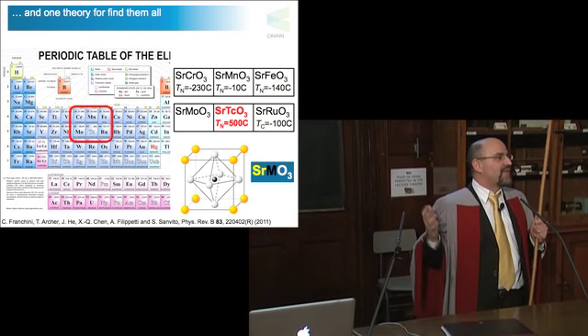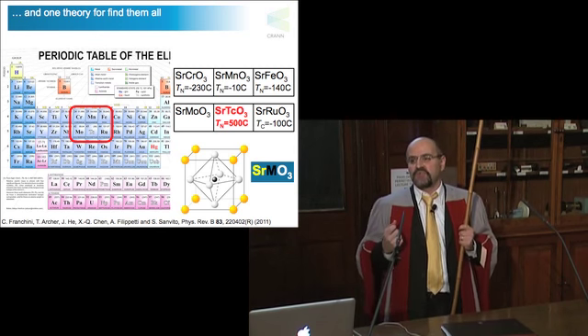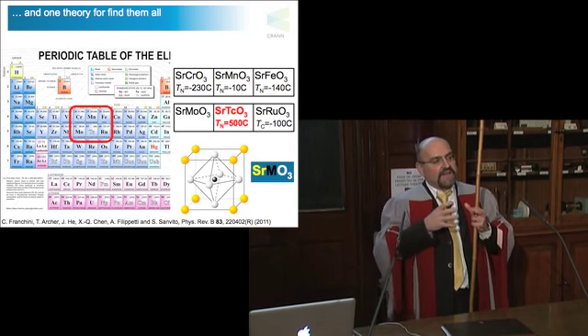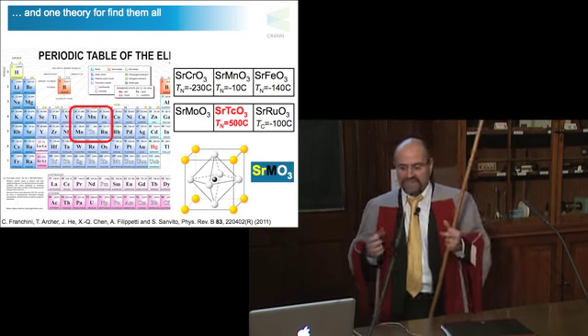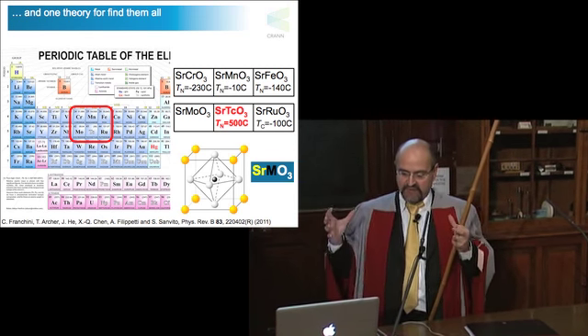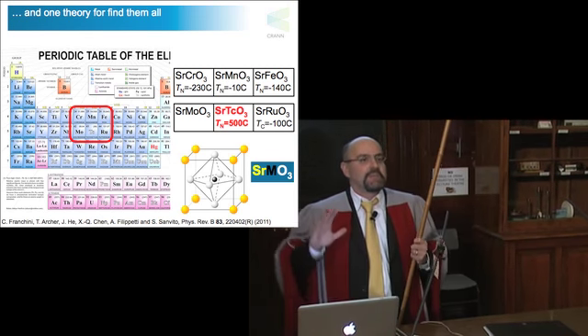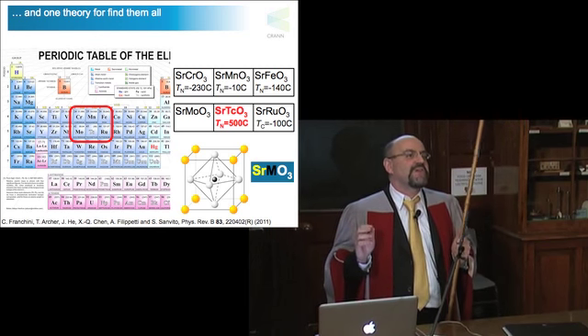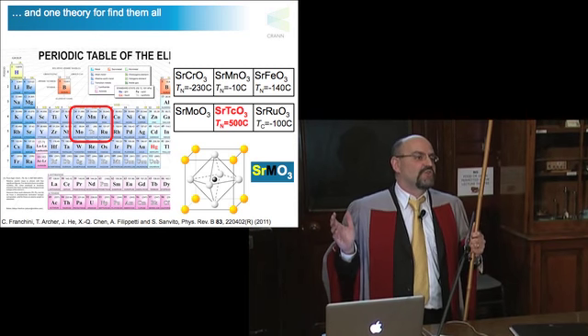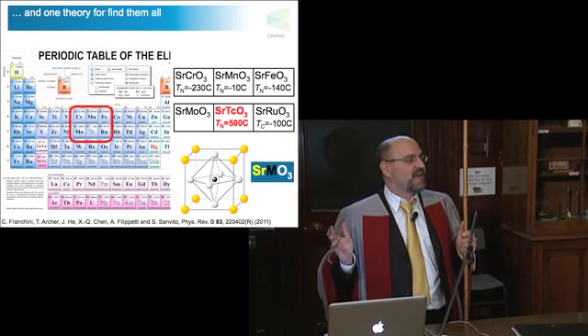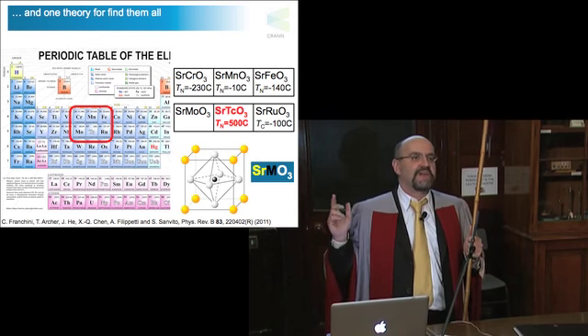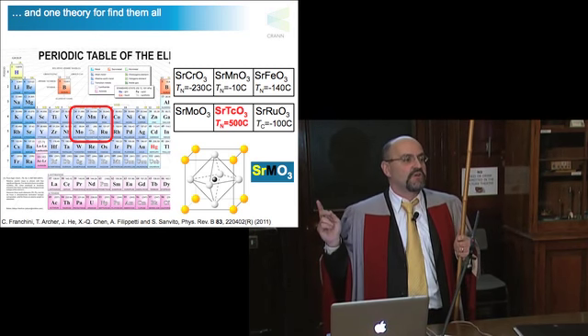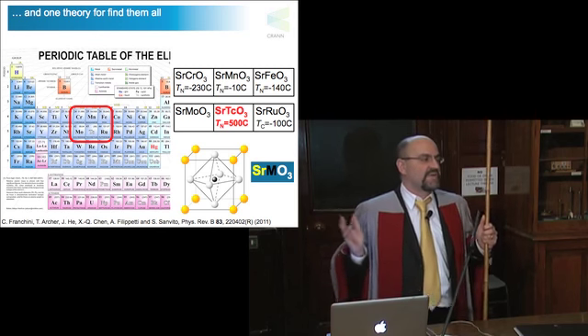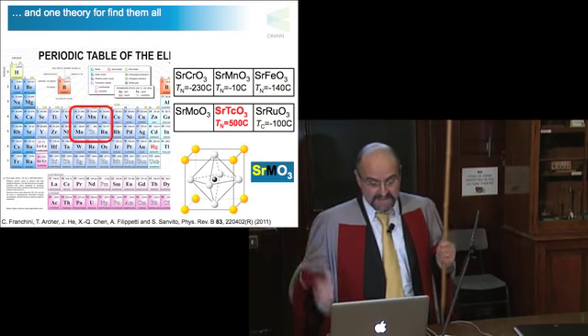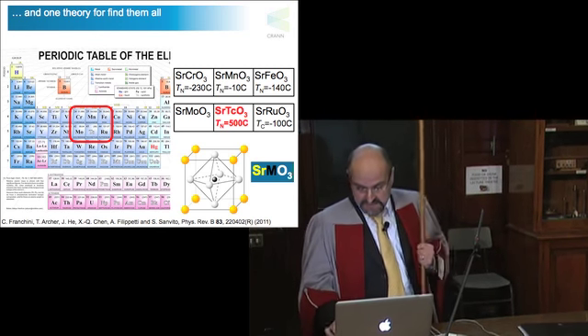And, well, the reason for that is a very subtle competition between having relatively large d orbitals and a very large distortion of the octahedral cage. But nevertheless, the point I want to make is magnetism really defies intuition. So unless somebody had grown this material or done the calculation, there was no chance for you to guess that the material was magnetic, at least for me.